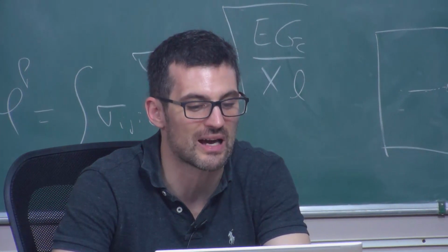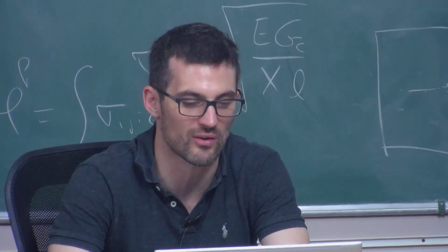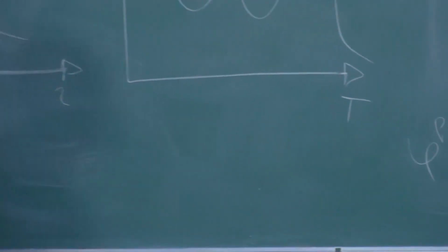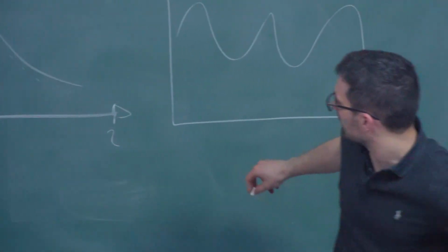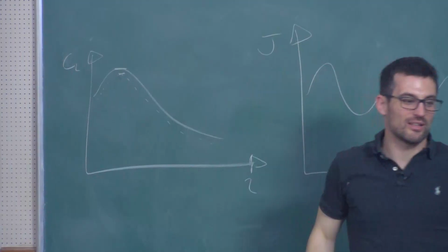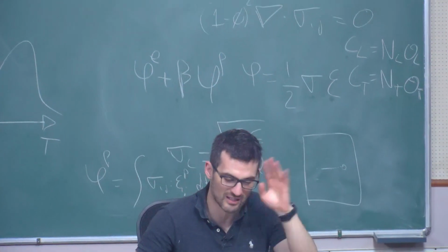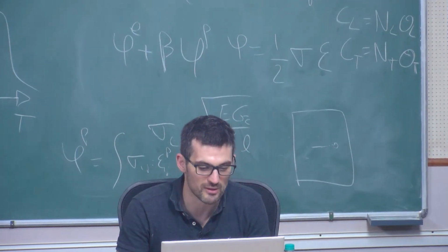This is what you see here. This is the hydrogen concentration, the maximum hydrogen concentration ahead of the crack. So I'm looking at this peak. Well, it's actually not the steady state one, but more like this one. I'm looking at that peak. I'm looking at that with finite element. This is a very simple calculation. There's no phase field, just a coupled diffusion deformation simulation.